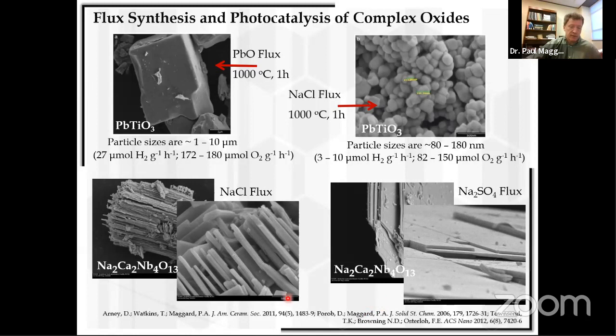Other prominent examples which could be discussed, sodium calcium niobate with a layered structure. You can make it in a rod-like format or a layered type format. And in this case here, you don't have a 3-dimensional structure, you have a 2-dimensional layered structure. And so by making the rod-shaped morphologies, you shorten the path length that the carriers have to reach the surface. Whereas in the layered type structures here, because the carriers are restricted to the plane of those layers, it is a much longer path length to get to the surfaces and to drive those catalytic reactions.